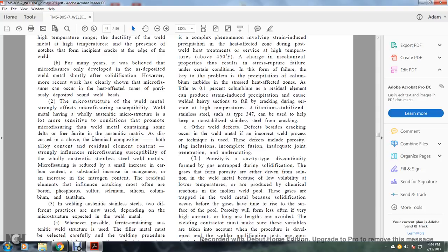As discussed above, the chemical composition, both alloy content and residual element content, strongly influences microfissuring. In wholly austenitic stainless steel weld metals, microfissuring susceptibility is reduced by a small increase of carbon content, a substantial increase of manganese, and an increase of nitrogen content. The residual elements influencing cracking most often are boron, phosphorus, sulfur, selenium, silicon, molybdenum, and tantalum.